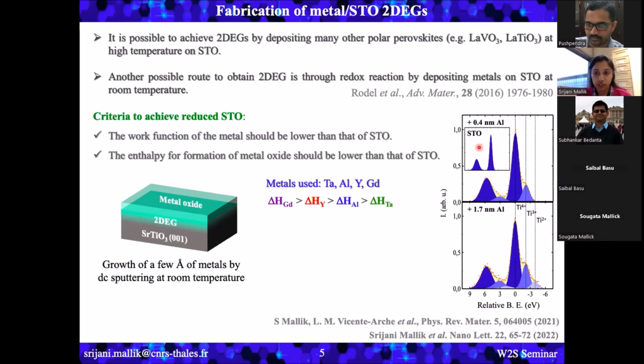And we can see only the peak corresponding to titanium 4+ is present. This means that it's fully oxidized and no oxygen vacancies are present in the system. But as soon as we deposited 4 angstrom of aluminium on top of this STO, immediately we could see that a peak corresponding to titanium 3+ is evolving, telling us that oxygen vacancies are created in the system. And as we increase the thickness of aluminium, the intensity of titanium 3+ increases, as well as titanium 2+ also shows up. So as we deposit more aluminium, more and more oxygen vacancies are created. And we can say that the two-dimensional electron gas is forming in our samples.